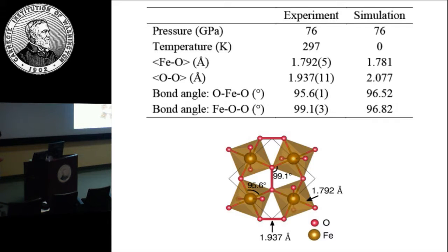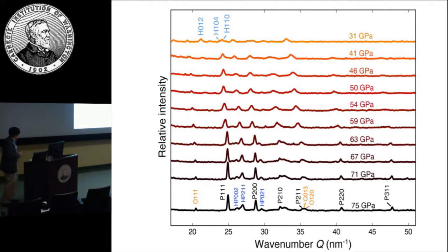This means that, like pyrite, the iron is actually 2+, but the oxygen is like O2. You can think of it as O2 dissolving in FeO. And when we release the pressure, at 31 GPa at ambient temperature, the pattern disappears. So this is quenchable from high pressure to room temperature, but not quenchable to ambient conditions.